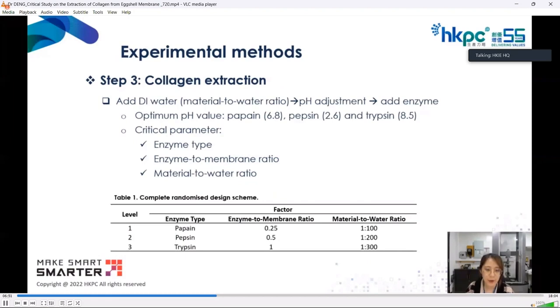The third step is to extract collagen from the eggshell membrane through the enzymatic hydrolysis process. The filter residue eggshell membrane was soaked in 1 mol per liter acetic acid. In this study, papain, pepsin and trypsin were used as biocatalysts for collagen extraction. The optimal reaction pH values of these three enzymes were 6.8, 2.6, and 8.5 respectively. We need to adjust the pH value of the solution first, and then a completely randomized design was used to study the effect of these critical parameters, such as enzyme type, enzyme to membrane ratio, and material to water ratio on the extraction rate of eggshell membranes. The completely randomized design is shown in Table 1.